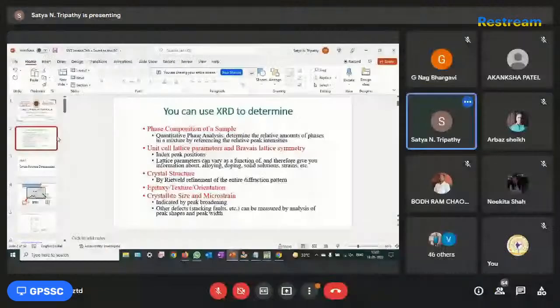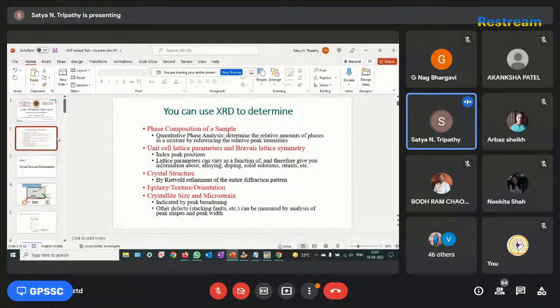Suppose you have a sample and you want to know its structure. Because there are reference patterns, you compare your synthesized sample pattern with the reference pattern and obtain the crystallographic information file. So you find the crystal structure of your own sample. Next is some structure analysis like texture, the orientation of the grains, crystallite size and microstrain.